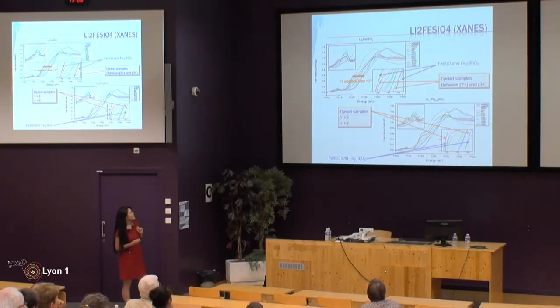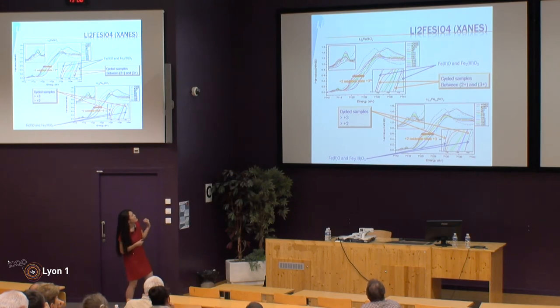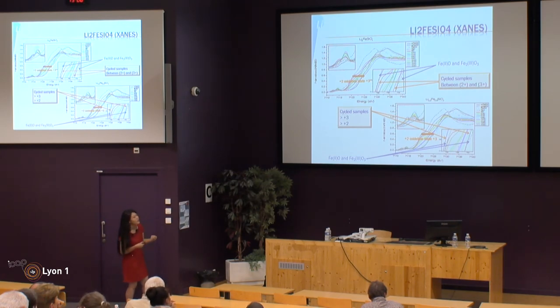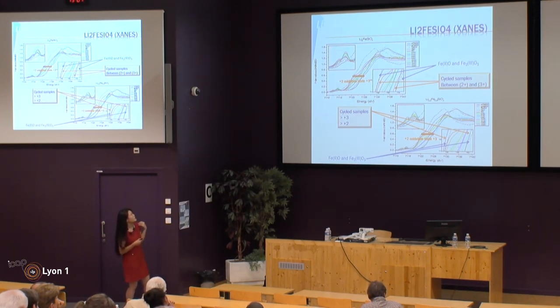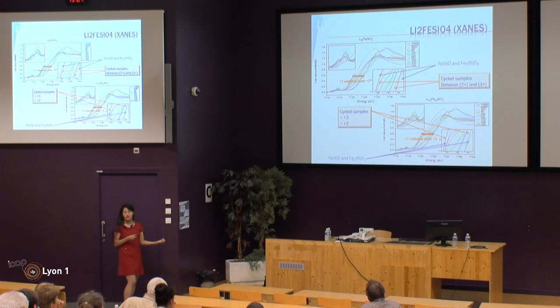This is our XANES spectra — there are many lines and it is quite difficult to see, but please come and ask me if you are interested. Looking at the pre-edge feature of lithium iron silicate: in the pristine sample we observed a doublet peak, confirming the existence of Fe2+. When we removed lithium from the structure, we started to see a singlet, confirming the oxidation of Fe2+ to Fe3+.